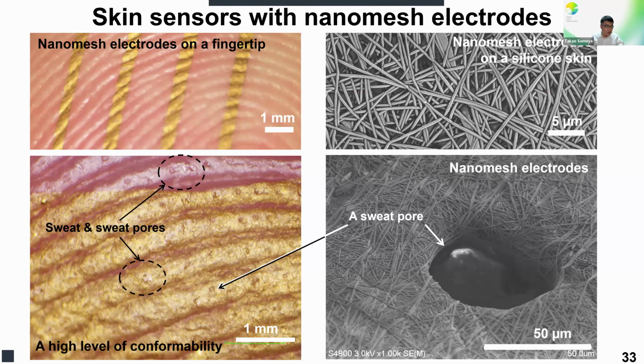So this is the nanomesh electrode attached on the fingertip. The shining part is a nanomesh, and the non-shining part is bare skin. So that used to be covered by the PVA, but that could be washed away completely, thereby this is bare skin. And the shining gold part looks like a continuous film, but if we look at the nanomesh layer by SEM, obviously that exhibits the porous structure.